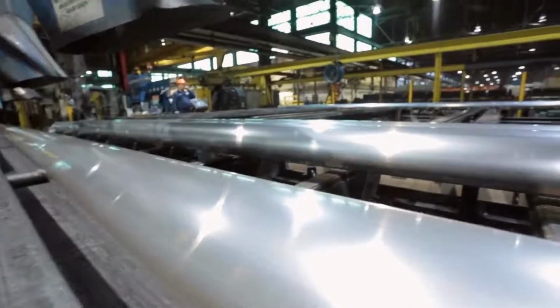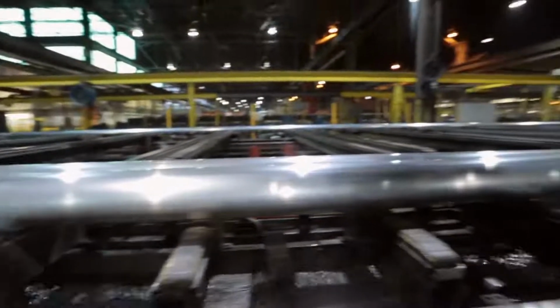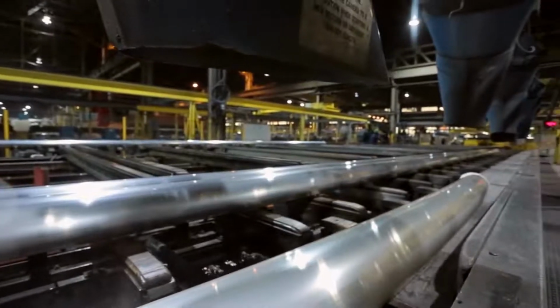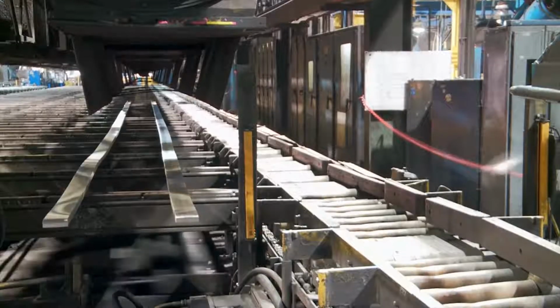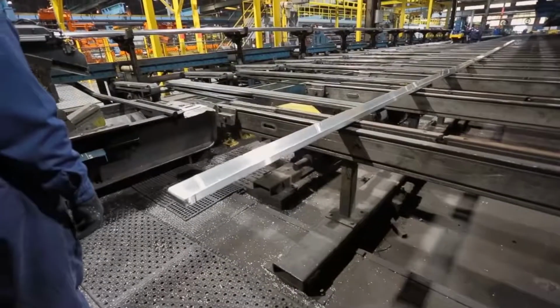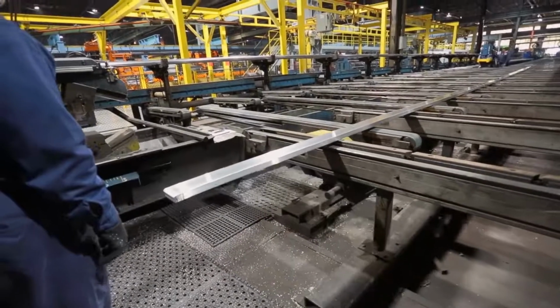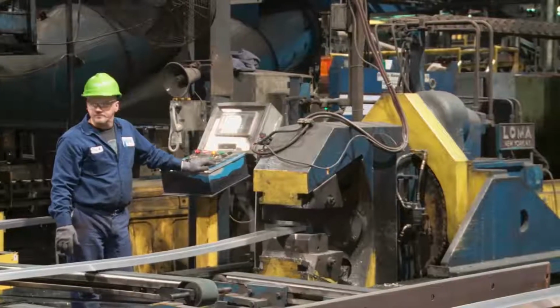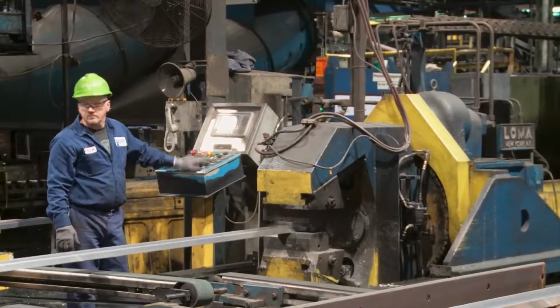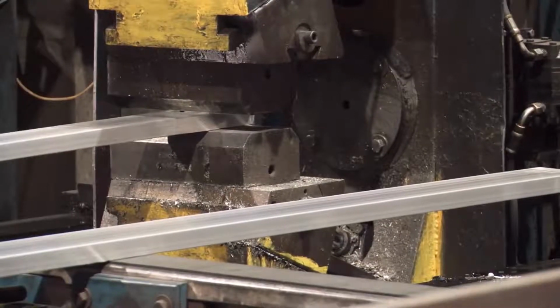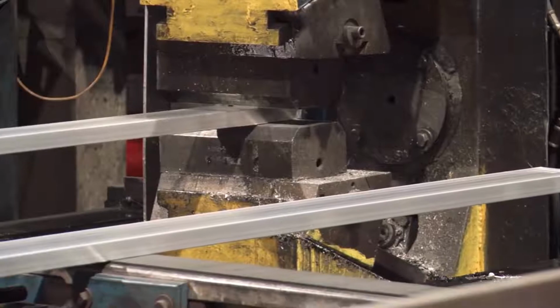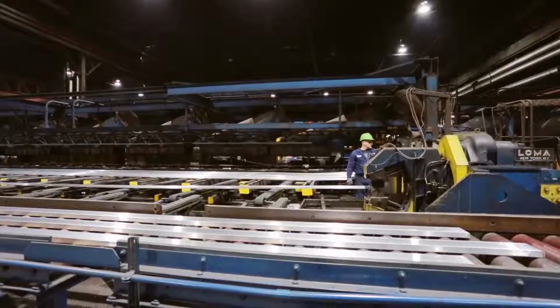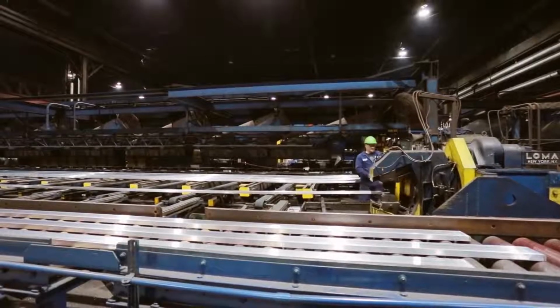Of course, whenever you introduce rapid cooling into hot metal, distortion can occur. The stresses formed cause the metal to twist and bow. We overcome that by placing the extruded length into a stretcher to control straightness and for stress relief. The typical stretch percentage for T6511 temper calls for a 1 to 3% stretch of the extruded length.